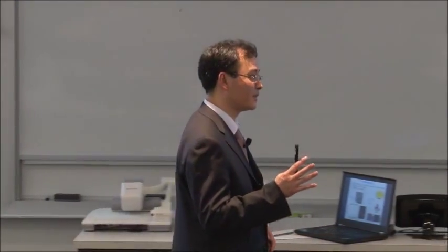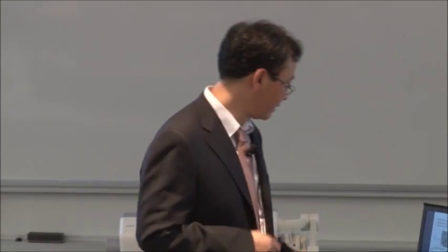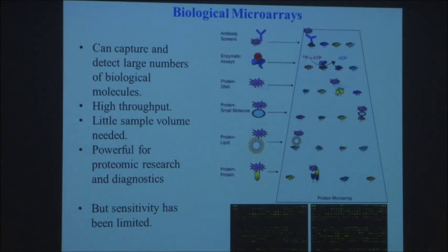And the other thing is that on the detector side, we could improve the capability of these cameras. I was talking to Professor Bond today, and he seemed to have a way to replace the InGaAs detector with a silicon detector by an up conversion mechanism. I think that could be very, very powerful for this technique as well. So detector and fluorophores. That's the first story, and I'll move on to these films I mentioned in the beginning for microarrays.